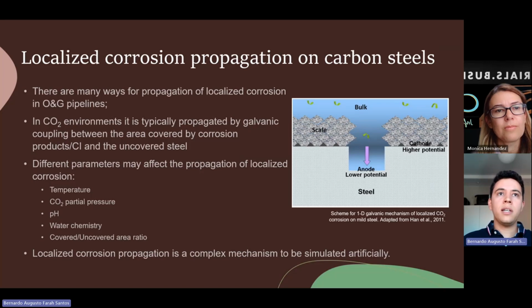One of the common ways of having this kind of propagation is due to what you said, the galvanic coupling that is established. And how is that in more detail? We can assume that usually on carbon steels, the pit is surrounded either by corrosion products or corrosion inhibitors, molecules that are adsorbed on the surface.